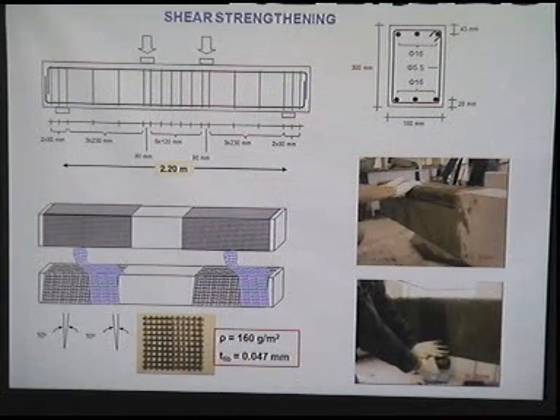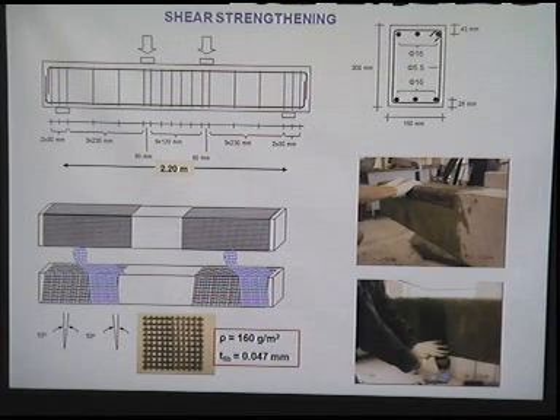The next step was to work on shear strengthening. I have been talking about confinement so far. Shear strengthening is quite frequently critical in beams and columns, so we designed members that would fail in shear intentionally. The failure mode should be shear, a brittle one, and those members were tested before strengthening and after strengthening with FRPs or TRMs.